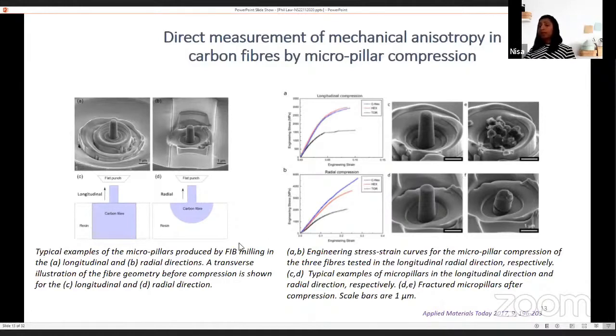We have conducted these studies on 3 different carbon fibers with various modulus. We found that tensile stiffness was significantly higher than the compressive stiffness in all these 3 fibers. And there is a connection between the degree of crystallinity and the stiffness properties.